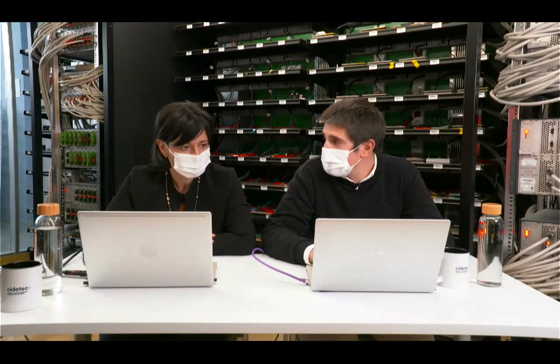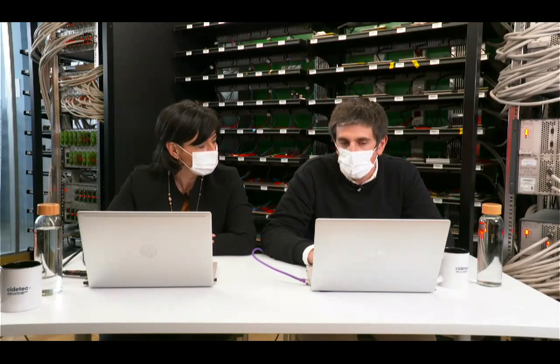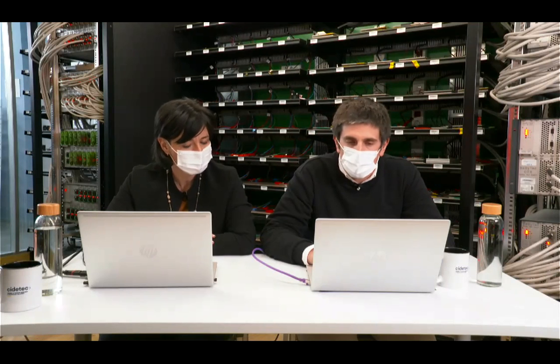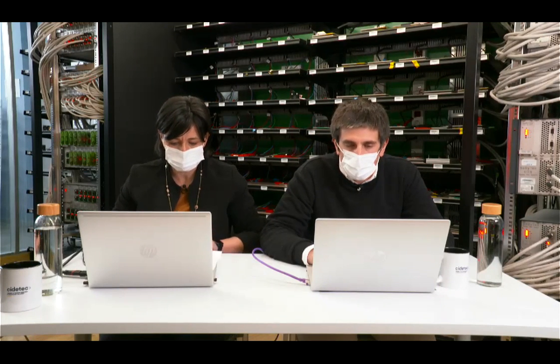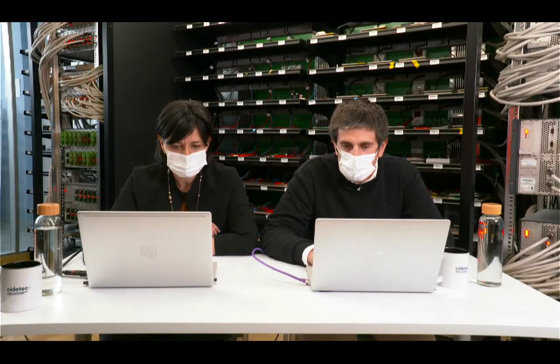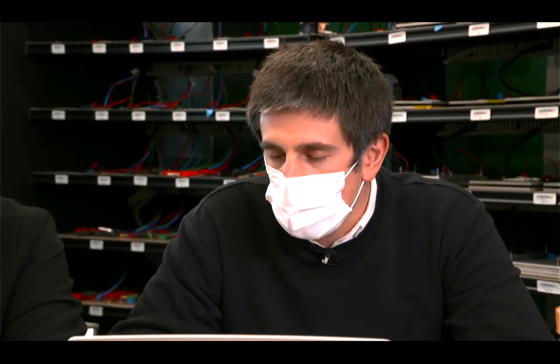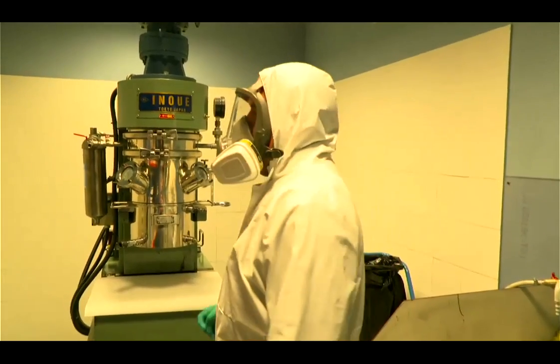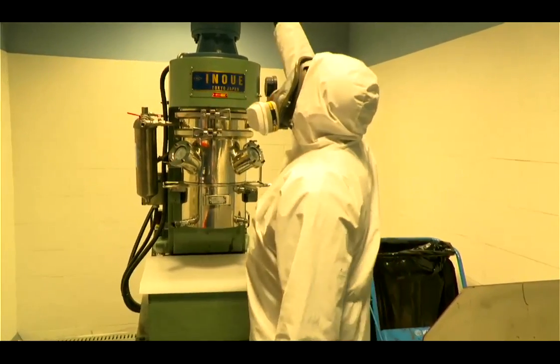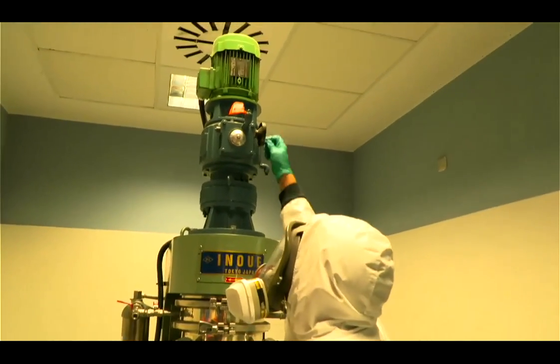Okay, so the first question is: which mixing times do we use on average for the different slurries? As Idoia mentioned in the introduction, for the laboratory work it is very important to have these timings in the different additions of the materials to the slurries. As for the average time, some of the slurries are done during the day, so maybe it takes 5 or 6 hours of mixing, and then we do the coating. But some of them need more time, and we add some materials the day before, so we have some mixing times overnight, depending on the formulations that we have set in the lab.